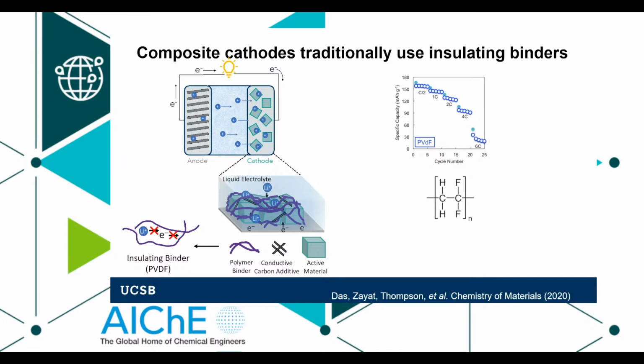So why is that? This is a real battery made with the standard PVDF glue, along with carbon black and LFP. And what you're seeing at the top is if we charge and discharge this battery relatively slowly, it has okay capacity. But as we go faster and faster, that's the 6C, is 6 charges and discharges per hour, you see the capacity fades almost to the point where it's non-operational. And that's because the LFP electrode is really not as active as we need it to be, and all of the resistive losses are piling up.